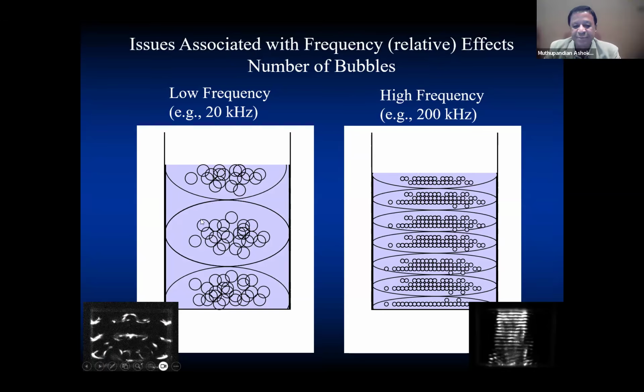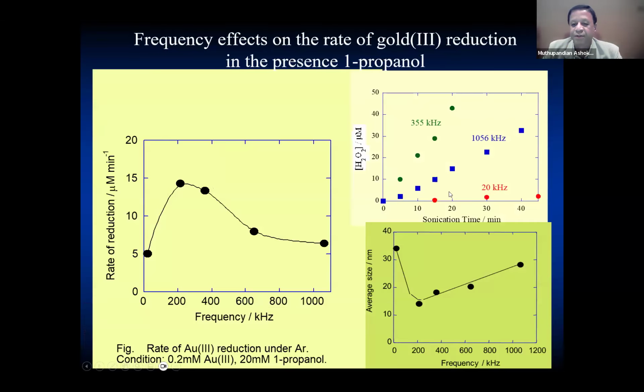So here is a schematic scenario between low frequency and high frequency. The photographs shown below are real-time pictures taken with two different frequencies, showing the sonoluminescence coming from these cavitation bubbles. You can see that at low frequency, you only have 3 active regions. At very high frequency, you have a large number of active regions generating the cavitation process. So that is the reason for this increase in the radical production from 20 to 300 kilohertz.